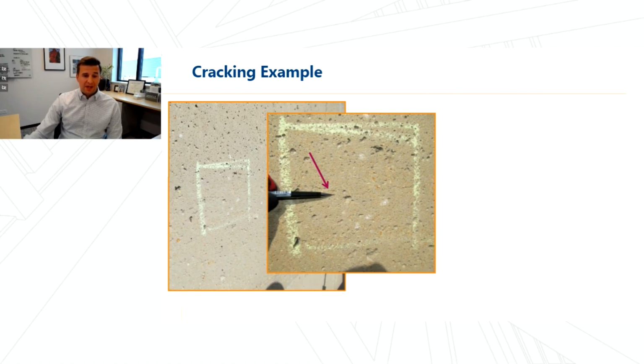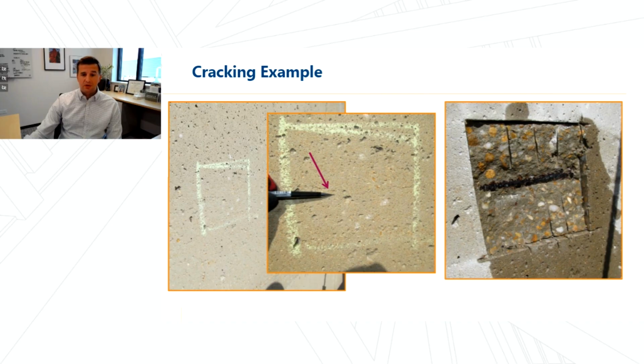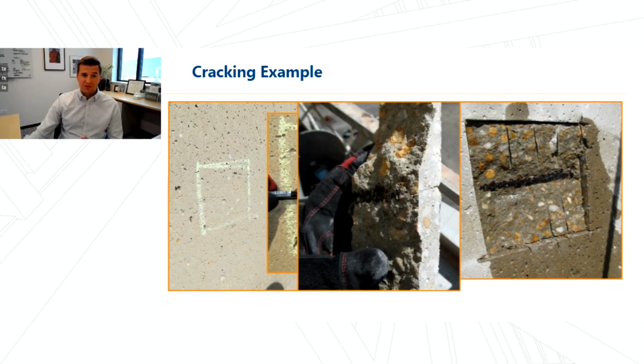So in the left-hand example, this horizontal crack, we made an inspection window, and the first thing that we see is corroded reinforcement, relatively shallow cover, and we can see that the crack follows a direct line from the corroded steel to the surface of the concrete. So in this case, we can characterize that this crack is caused by corrosion, and that might inform our expected condition of the structure moving forward or repair considerations.